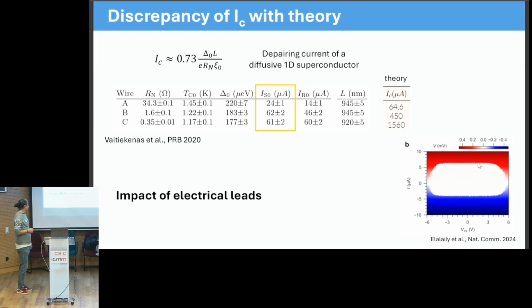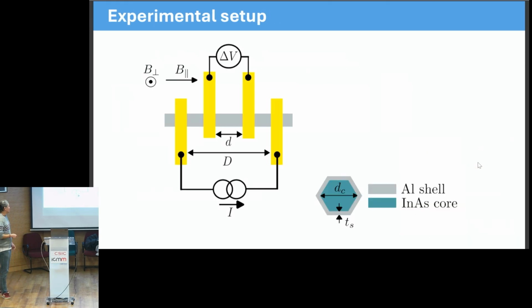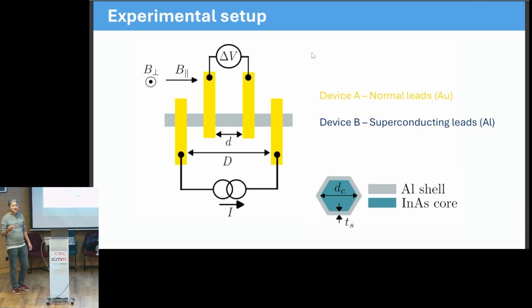So we tried to study this, and we observed a very strong effect of the type of electrical leads that we use to contact the wire. So we did an experiment, as I said, using the same geometry as in the previous paper I had mentioned, with the difference here that we studied the impact of the electrical leads. So we studied devices which had normal electrical leads and devices which had superconducting leads.